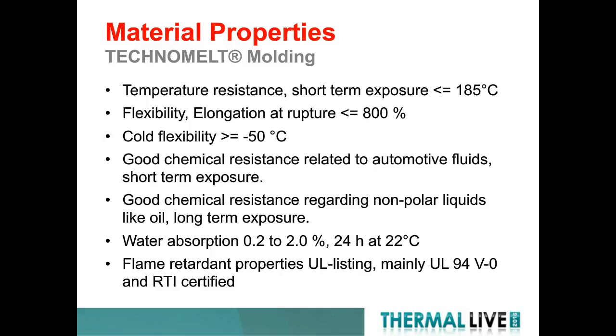The materials have good chemical resistance related to automotive fluids for short-term exposure, and generally good chemical resistance related to non-polar liquids like oil, and those can be done in long-term harsh environments. It is a plastic, again, so it does absorb moisture, 0.2 to 2% in 24 hours at 22 degrees C. However, it reaches a saturation point, where no more moisture would absorb into the material, and the migration into the electronics is null. I mentioned before that there are flame retardant properties. Many of the materials are UL listed at 94V0, and some are even RTI certified.